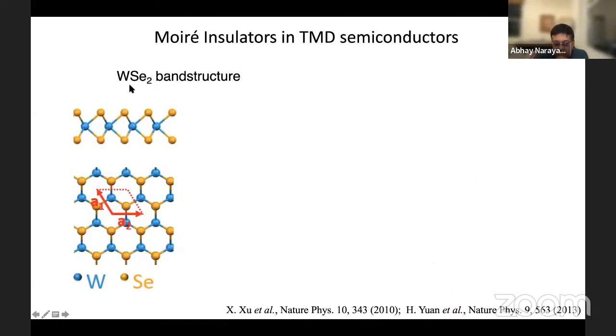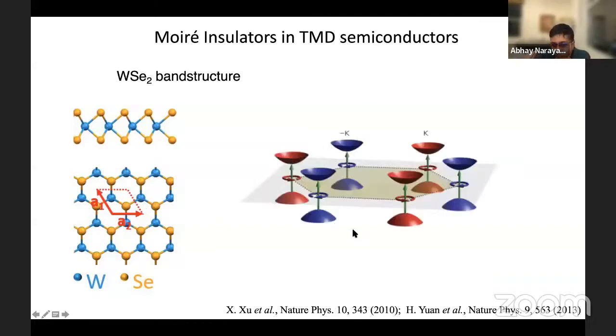Now, this material is a pretty boring semiconductor in monolayer form. It's a close cousin of graphene. It consists of tungsten and 2 selenium atoms per unit cell. And looking from the top, it kind of looks like graphene. If you ask what the electronic structure of this material is, it looks like graphene with a large band gap. So it has conduction bands and valence bands, and there are 2 valleys, one at the K point, one at the minus K point.